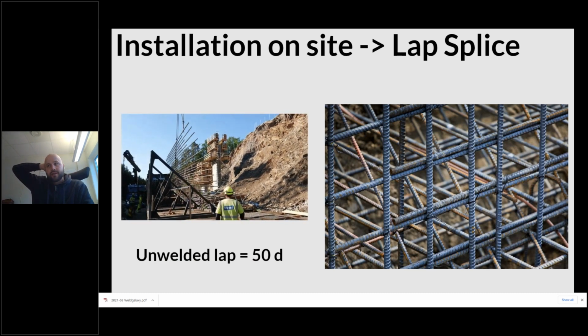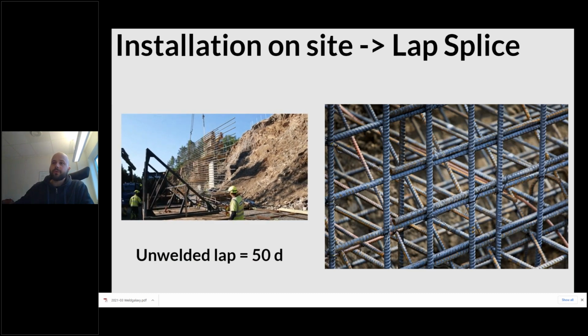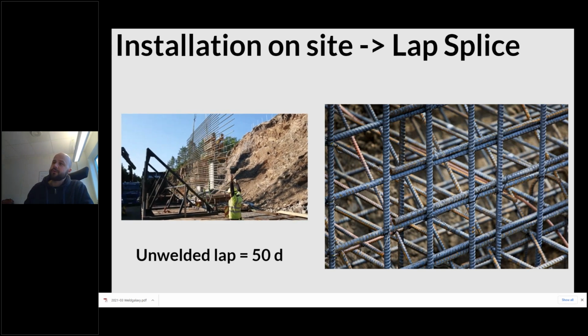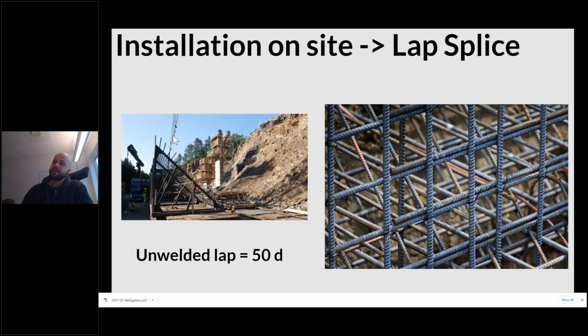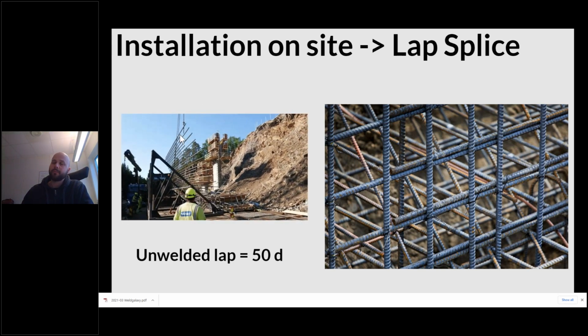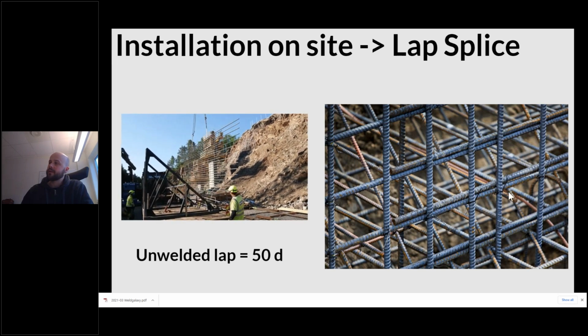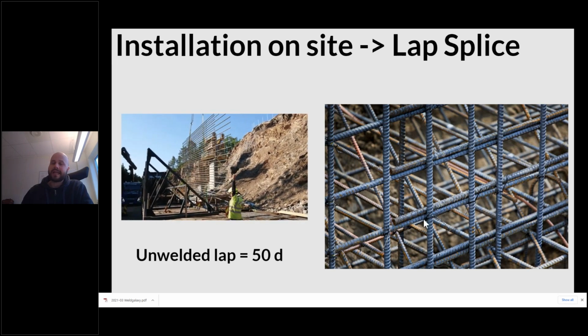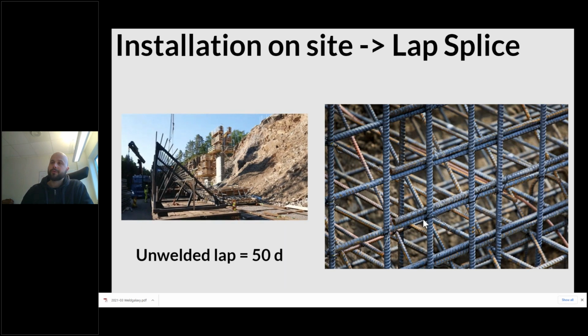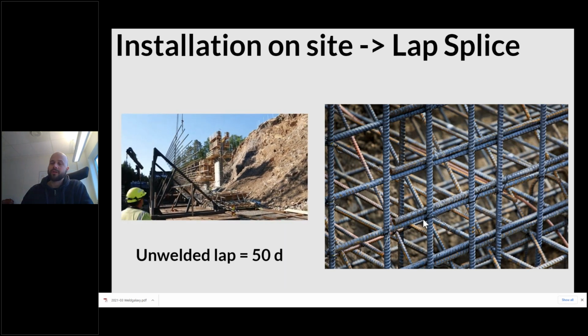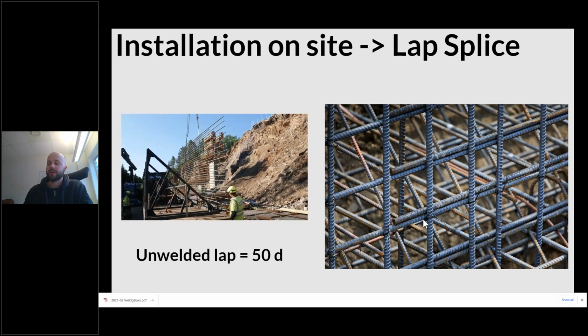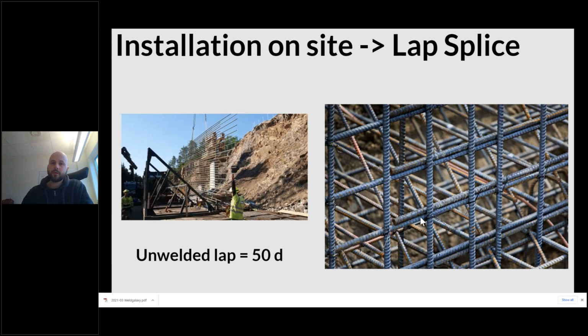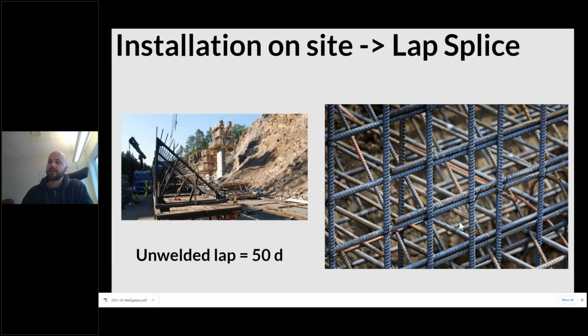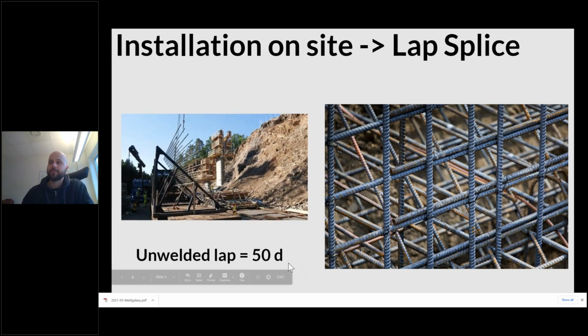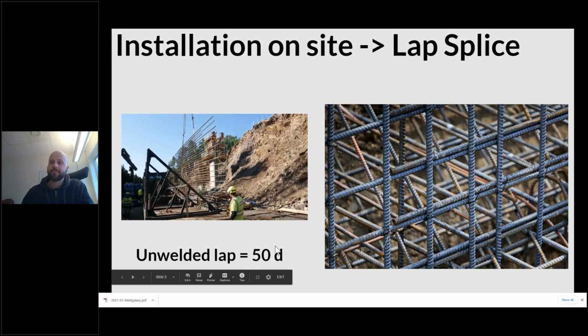Once you have done that, the next step is that you install the rebars on site. On the left side, this is a mesh that we have made for a bridge project. And on the right-hand side, you see something called a lap splice. Traditionally, the way you join different rebar cages or different rebars together on the construction site is an unwelded lap splice. And here the rule of thumb is that you use 50 times the diameter as a lap length.